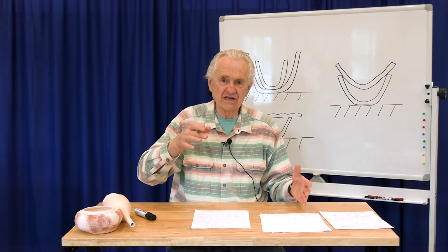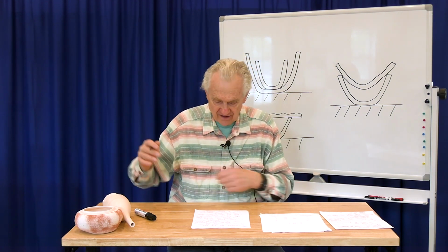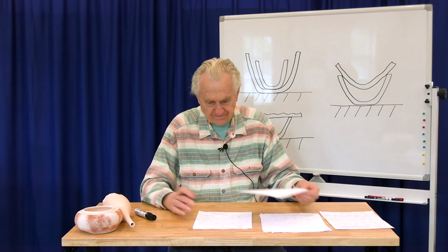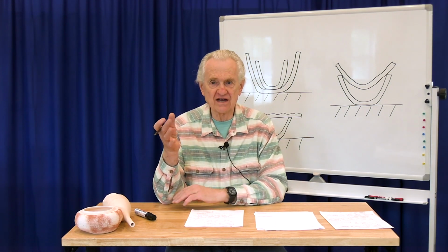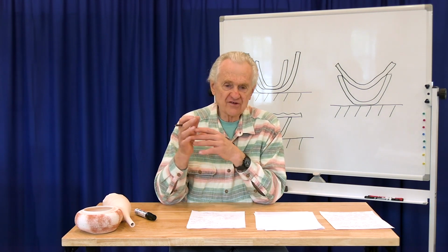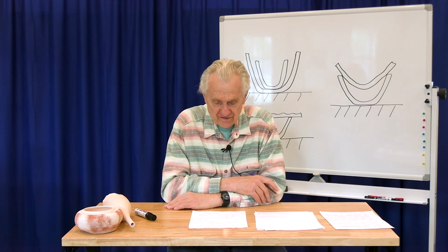You need to go slowly enough so that the water can be removed, along with all the other processes we're talking about, long before the glaze starts to melt. So essentially, you still need to perform a bisque; you're just not unloading and reloading the kiln. Another thing, as I mentioned before, is to air dry the pots thoroughly before you put them into the kiln, if you can. If some of the pots are a little too close to the elements, at least if they're thoroughly dry, you're not going to get steam explosions early in the firing.